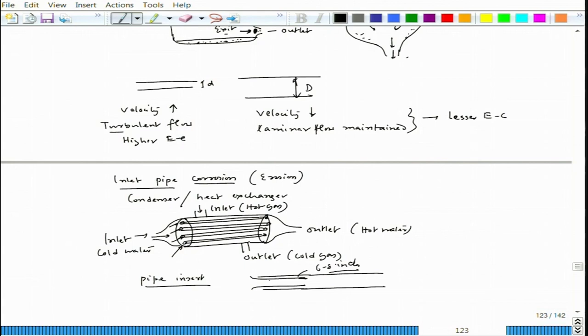So this insert is actually now the inlet water entering through that insert into the main heat exchanger pipe. So now in this portion at least there is no effect of the turbulence. Of course, when this water goes out from this particular part, close to the exit of that insert, we can have a little bit of erosion effect. So here erosion effect would be there.